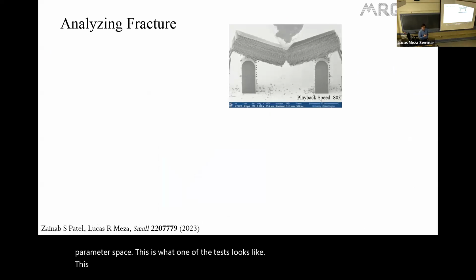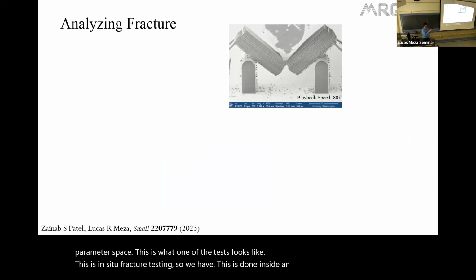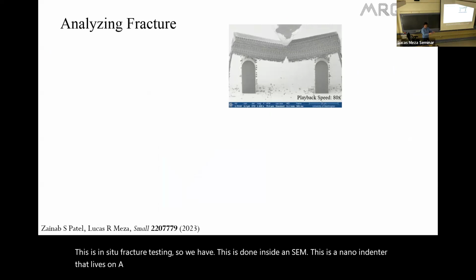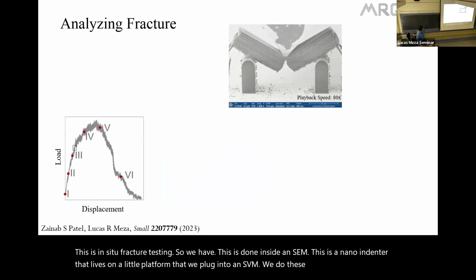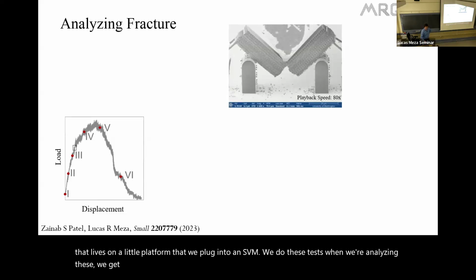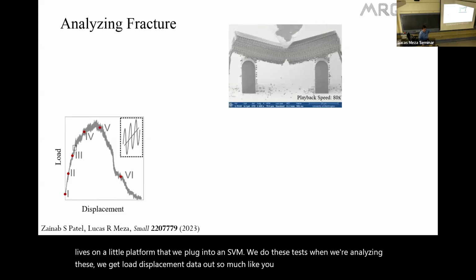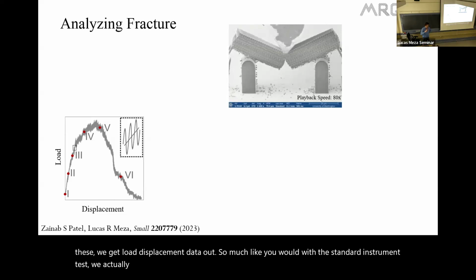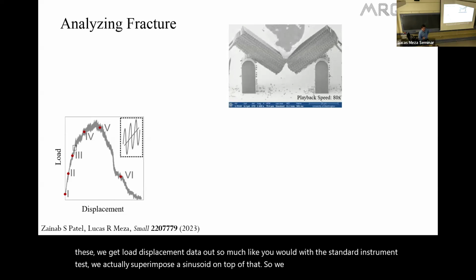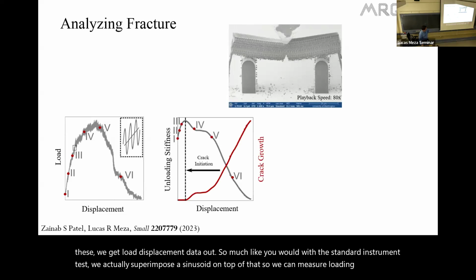This is in situ fracture testing. So this is done inside an SEM. This is a nanoindentor that lives on a little platform that we plug into an SEM, and we do these tests. When we're analyzing these, we get load displacement data out. So much like you would with a standard Instron test, we actually superimpose a sinusoid on top of that, so we can measure loading stiffness kind of continuously during the process.